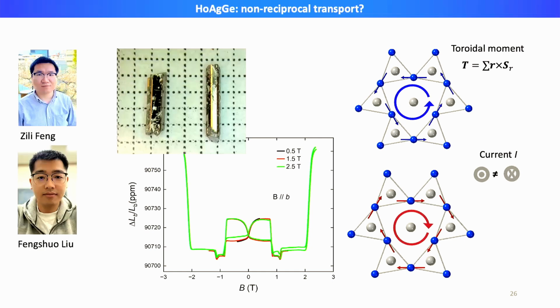in this state. So a peculiar feature of both of these states is that they would both break the mirror symmetry, with the mirror plane being the plane you're seeing here on the screen. And at a very simple level, this would induce a difference in the transport property of the system, with the current flowing into the board and the current flowing out of the board. And this is called non-reciprocal transport. And in principle, the non-reciprocity of the transport response would also be opposite for the two different magnetic domains.